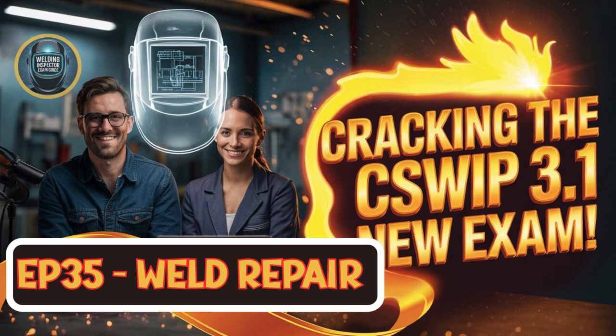Right. Lastly, what about as-welded repairs? That means doing the repair without any post-weld heat treatment, right? It sounds like you're skipping a potentially important step, but is it common? It is quite common, actually. Repair without PWHT is pretty normal in situations where the original weld wasn't heat treated either. If the original design didn't require it, often the repair doesn't, assuming conditions haven't changed drastically. But not always. Not always.